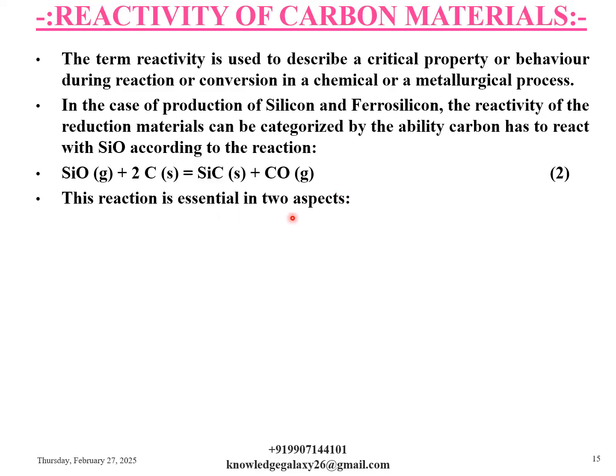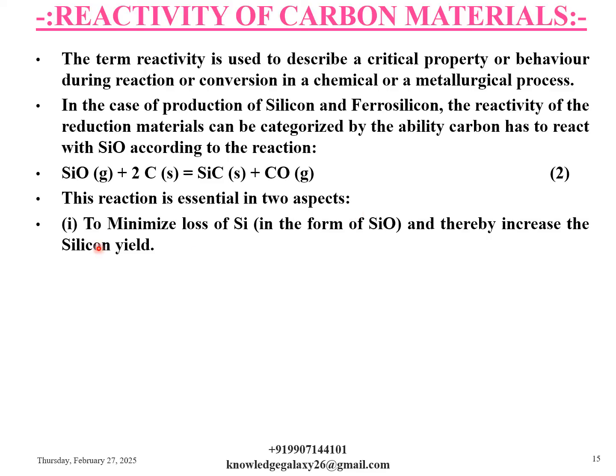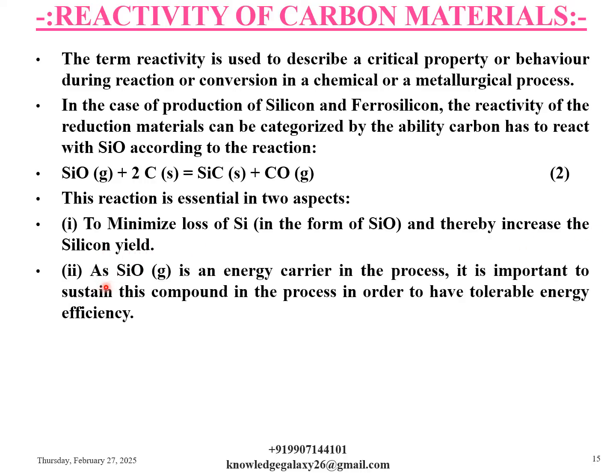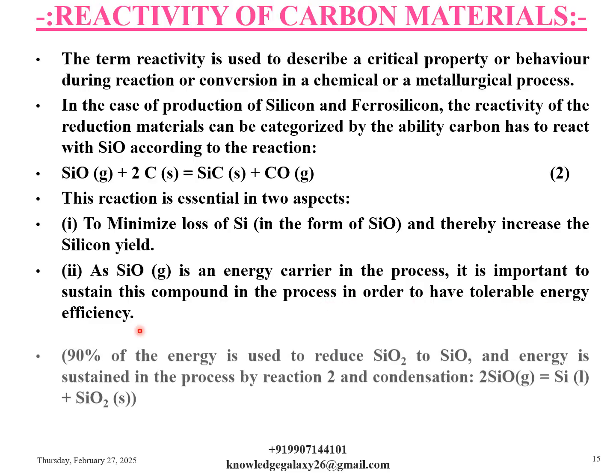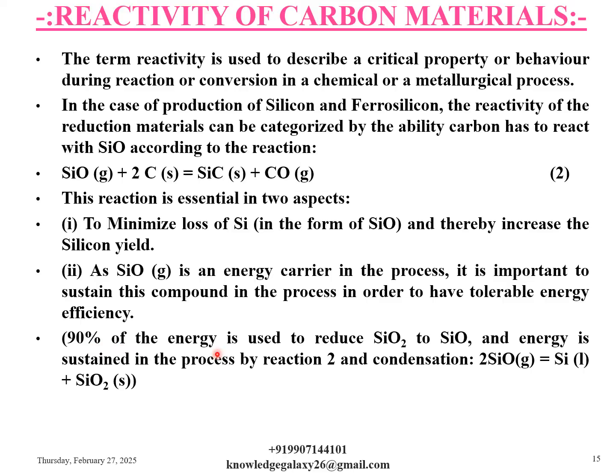This reaction is essential in two aspects. The first aspect is to minimize loss of silicon in the form of SiO and thereby increase the silicon yield. The second aspect is, as SiO gas is an energy carrier in the process, it is important to sustain this compound in the process in order to have tolerable energy efficiency. That is, 90% of the energy is used to reduce SiO2 to SiO, and energy is sustained in the process by reaction number 2, and condensation, which is 2SiO (gas) gives silicon (liquid) + SiO2 (solid).